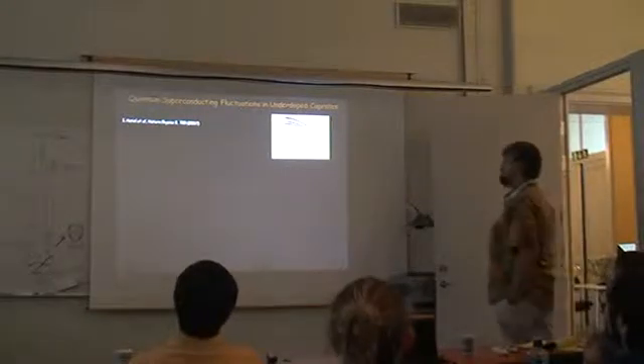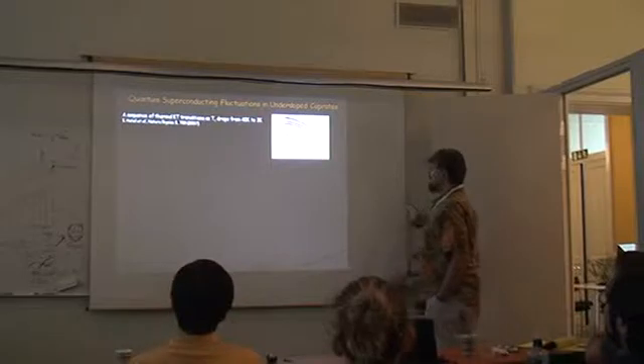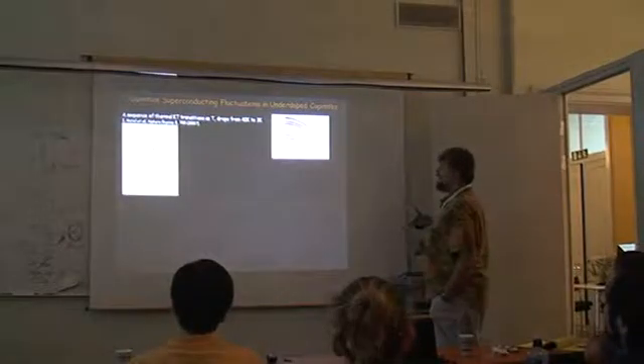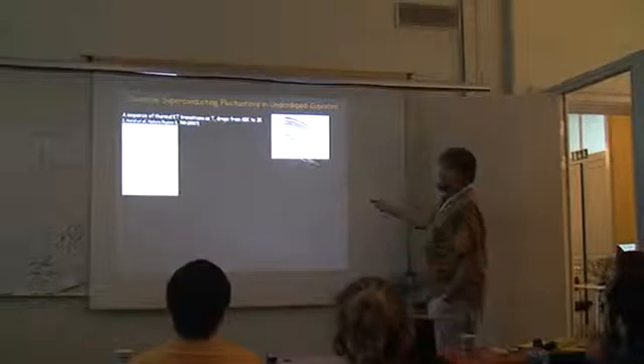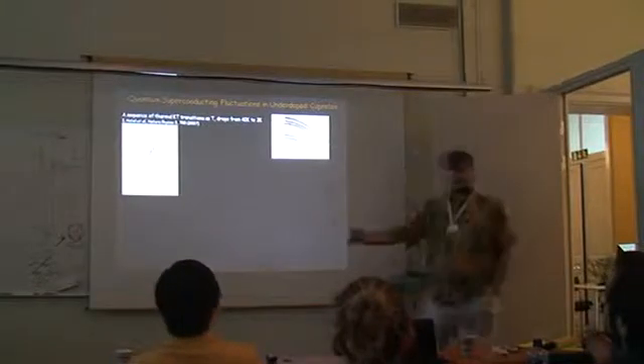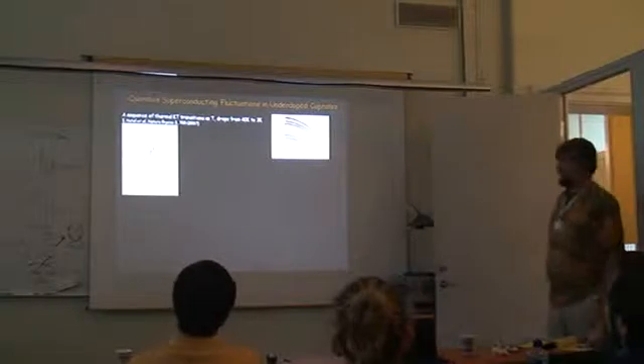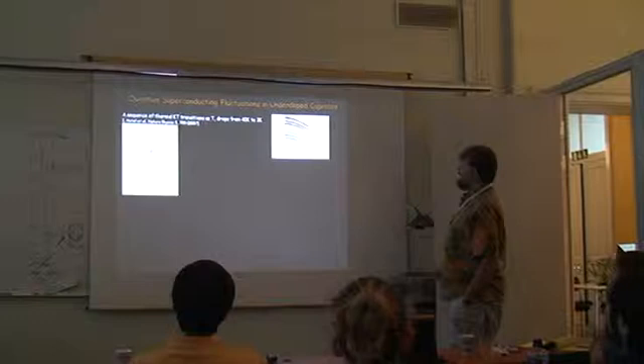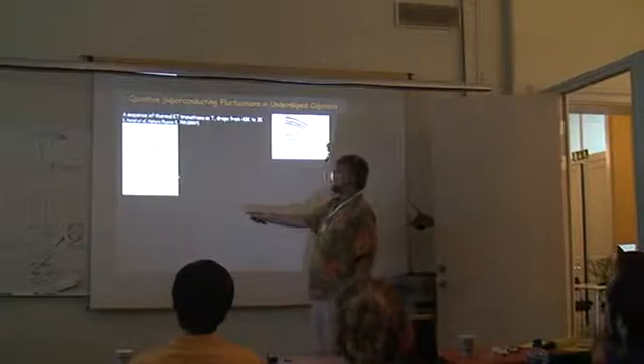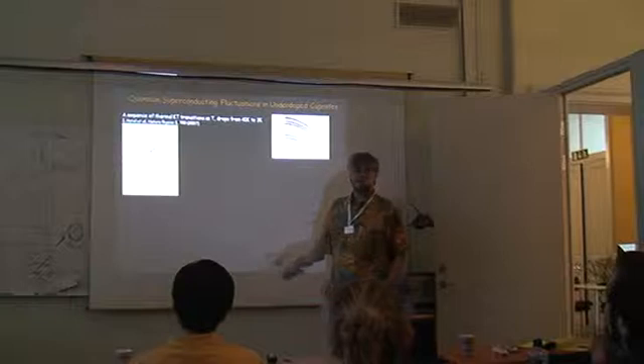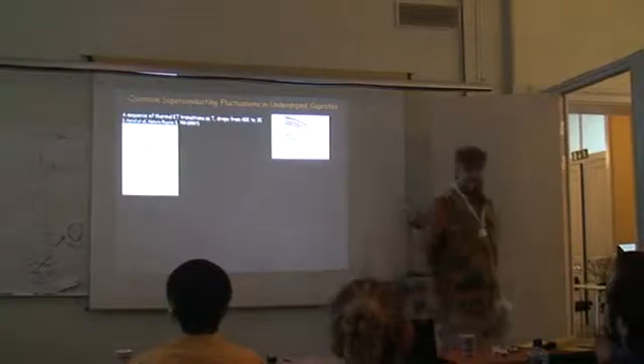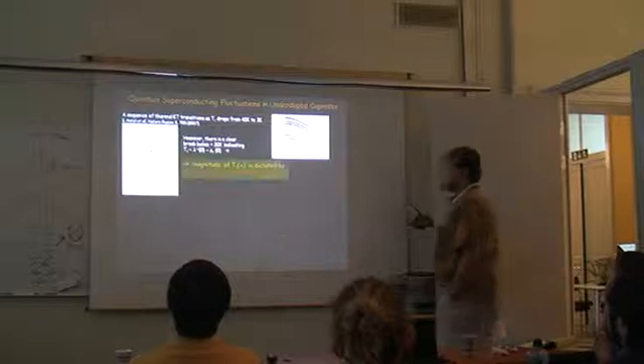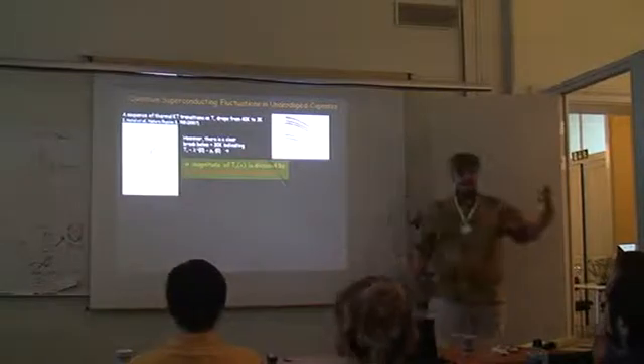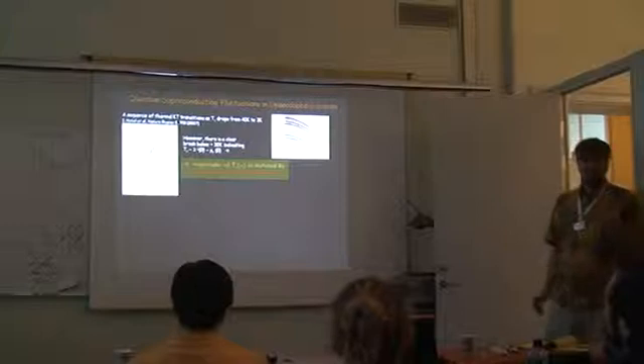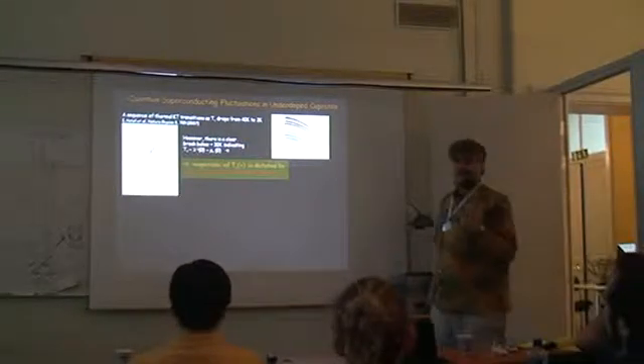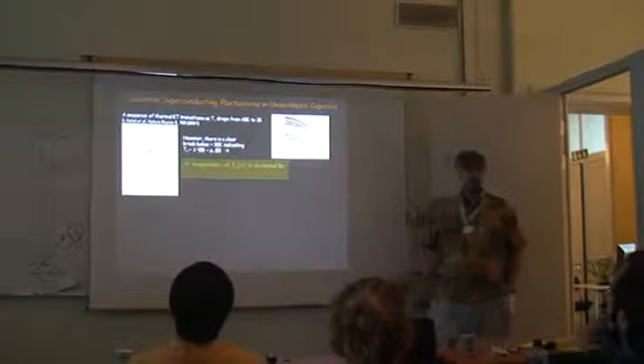So there are many other experiments along these lines that indicate that something like this is going on, meaning superconductivity destroyed by quantum disordering. Very nice measurements of superfluid density by Tom Lemberger group at Ohio State. They show a suppression of measured TC in films as you approach this critical point, if you will, on the underdoped side. And they measure that superfluid density and correlate TC to superfluid density at 0 temperature. And it turns out they scale in a very special relation, which indicates that, in fact, the magnitude of TC, superconducting transition, at finite temperature is, in fact, dictated by the superfluid density at 0 temperature in a relation that is characteristic of quantum superconducting fluctuations.